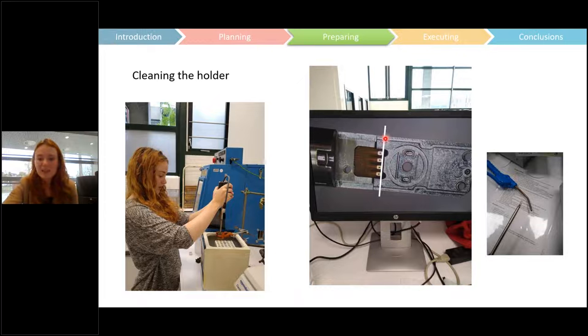And I dip the tip of the holder up to this line, just below the gel pads. That's where I aim for, in the ethanol, preferably very clean ethanol. And I sonicate it for 20, 30 seconds, nothing more. The idea is that sometimes in the grooves, you will get silicon nitride shards from where people have incorrectly picked up the chips and chipped them.